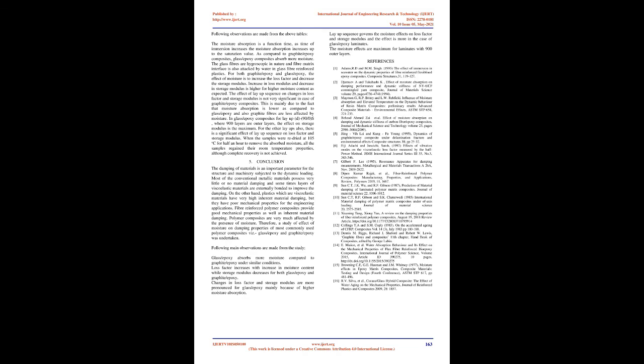Glass/epoxy absorbs more moisture compared to graphite/epoxy under similar conditions. Loss factor increases with increase in moisture content while storage modulus decreases for both glass/epoxy and graphite/epoxy. Changes in loss factor and storage modulus are more pronounced for glass/epoxy, mainly because of higher moisture absorption. Layup sequence governs the moisture effects on loss factor and storage modulus, and the effect is more in the case of glass/epoxy laminates. The moisture effects are maximum for laminates with 90° outer layers.